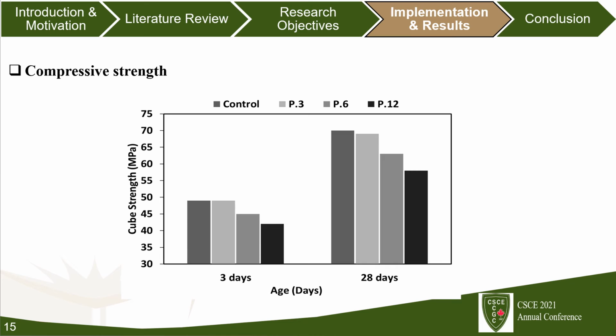For the compressive strength, the test was executed to evaluate the mechanical properties while incorporating the phase change material. Generally, as you can see in this graph, the dosage affected the mechanical properties of the self-compacted mortar. At age 28, the mixture incorporating 3% of microencapsulated phase change material reported a similar compressive strength, as you see here, to the